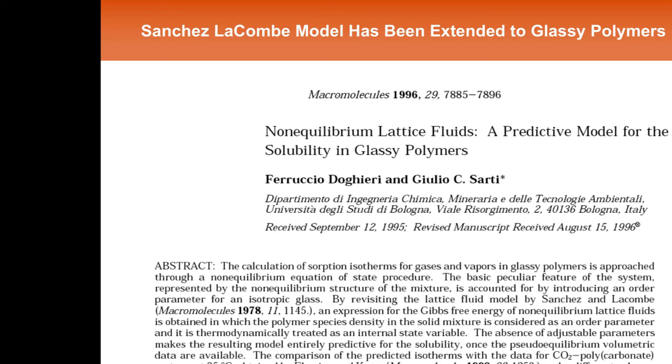And some of these, the swelling here, you may imagine that you take a piece of plastic and just contact it with a gas and it doesn't swell much. Well, if you get the temperature low enough and the pressure high enough, this is showing like 20 volume percent swelling. And the extent of dilation is just really easily predicted from the concentration of the methane and butane in the polymer times their partial molar volumes that you get from just pure gas swelling experiments. So this is an example of additivity of volume, right? You have polymer, you mix some butane in it, you mix some methane in it, and the whole mixture swells just according to volume additivity.